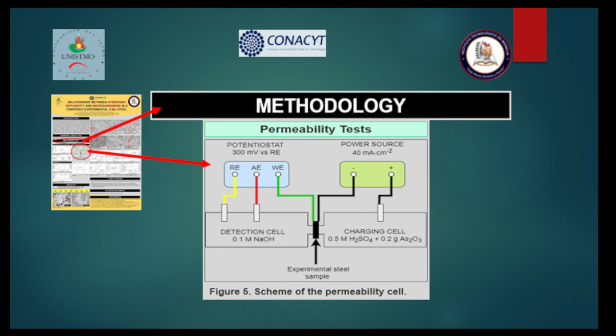The electrochemical hydrogen permeability tests were performed by means of the double hydrogen permeability cell standardized by Devanathan and Stachurski. The experimental configuration consists of a charging cell with a 0.5 molar sulfuric acid solution with 0.2 grams of arsenic trioxide to prevent hydrogen recombination, and a detection cell with a 0.1 molar sodium hydroxide solution, as shown in this figure.